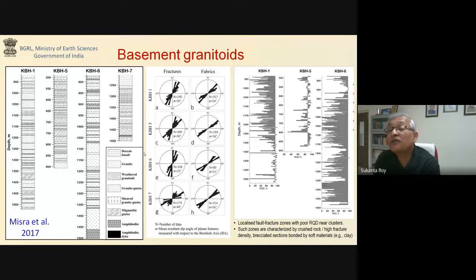In some of the other boreholes, of course, like KBH5, you can see in the middle panel, the rock quality designation is relatively much better. But in KBH6, again, almost the entire basement section is highly fractured, which means that we only got small pieces of core, less than 10 centimeters. So these localized fault fracture zones with poor RQD were mostly found near the earthquake clusters. And in such zones, a more detailed look at the core showed that they are characterized by crushed rock, very high fracture density, and brecciated sections, which were cemented by soft materials, mostly clay.